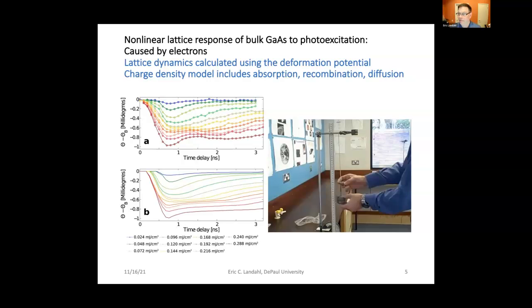But we move out of the probe depth very quickly. So although the heating is happening in this case quite slowly, the electrons are continuing to move. And thermal diffusion, of course, is very, very slow. So the electrons diffuse away quickly, or at least that would be our interpretation with this type of data. In fact, I think the electrons, especially at high excitation density, are usually believed to be supersonic. Okay.